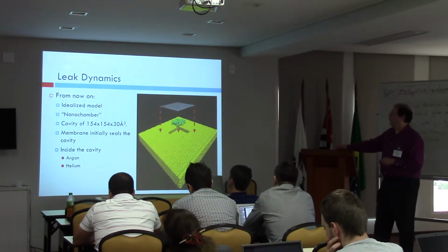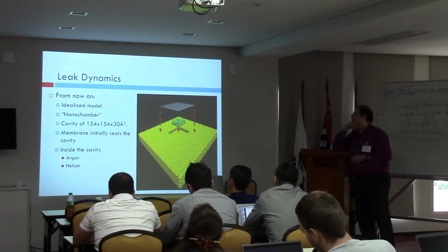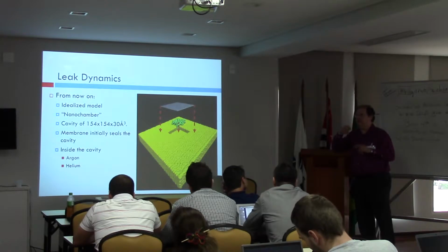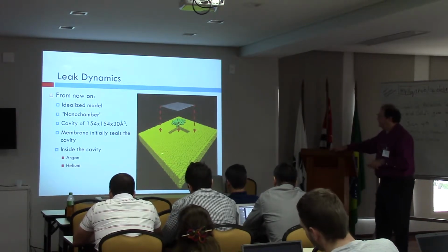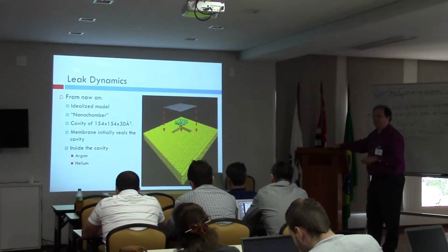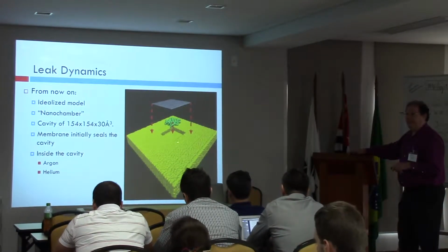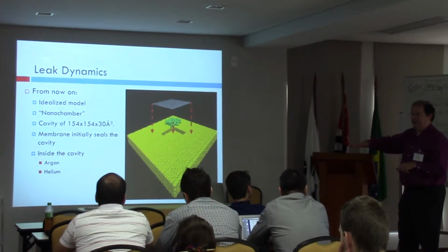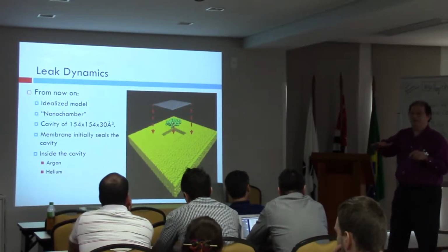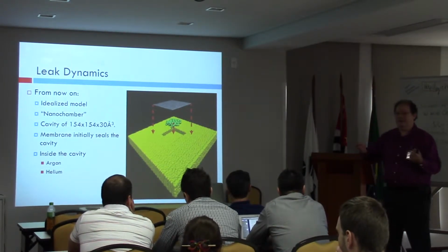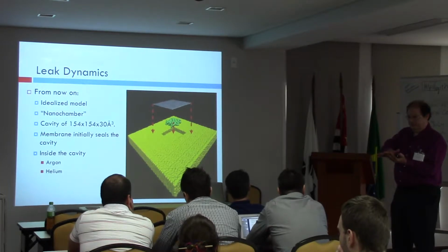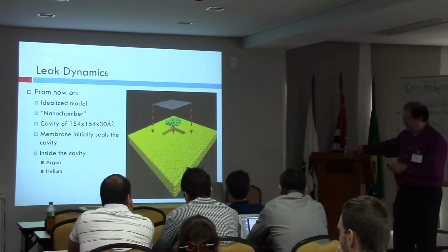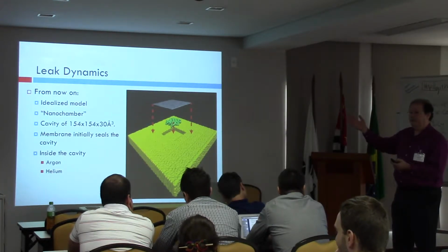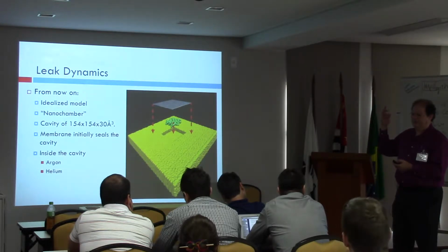Some years ago, the group of McEuen at Cornell did this very elegant experiment. In this case, they were interested in extracting the elastic constant for graphene. What they did, they created a pit on a silicon oxide substrate, filled it with gas, and deposited the graphene membrane. Because the van der Waals interaction is, again, very strong, you do not need contacts. It's a self-sealing system. So they heated the system, measured the deformation, and extracted the elastic constant.